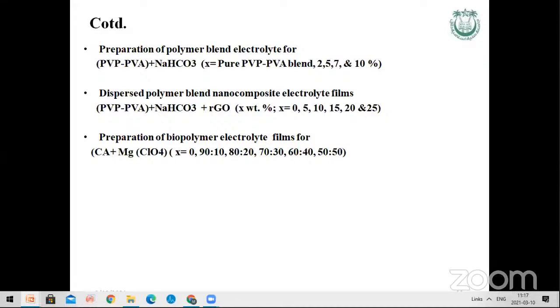In our study, we have prepared blend polymers based on PVP and PVA with several concentrations of salt, and we also disperse the nanofiller, RGO, in different weight percentages. We also prepare a biopolymer electrolyte, cellulose acetate with some magnesium salt.